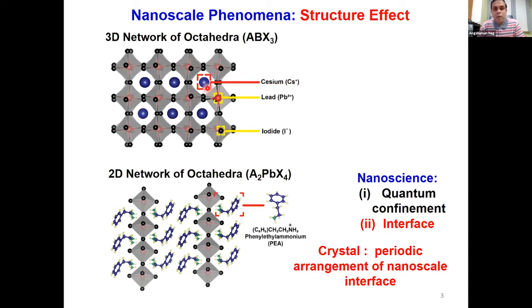Now, if the size of the void increases too much, something like when we get phenylethyl ammonium as an A-site cation, the inorganic octahedra get separated from each other, and in between you see this kind of organic layers. So what you get is atomically thin 2-dimensional lead halide layers, and this gives you the quantum confinement. And then more importantly, you get the interfaces between the organic and inorganic layers, and these are nanoscale interfaces that are repeating over the 3-dimensional space. So you can see here, the entire crystal becomes a periodic arrangement of nanoscale interfaces. And that kind of nanoscale interfaces gives rise to interesting properties, and some of those I'll be discussing today.